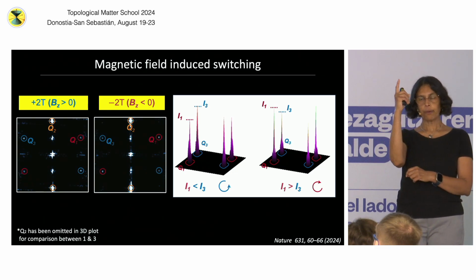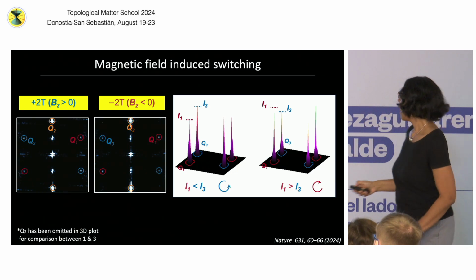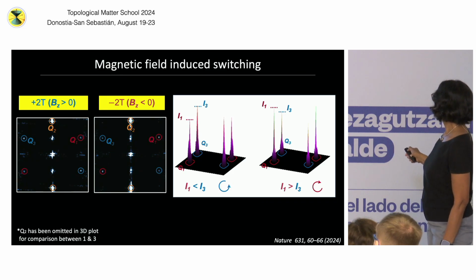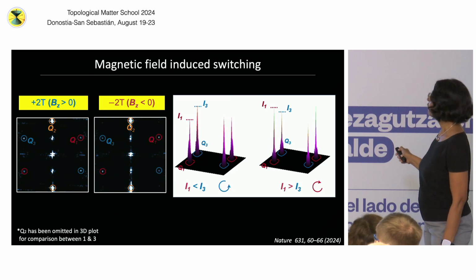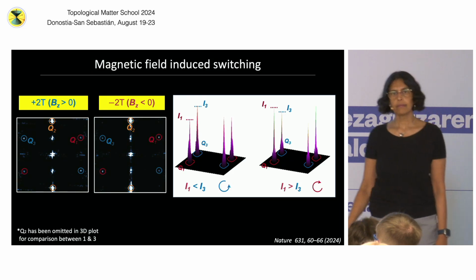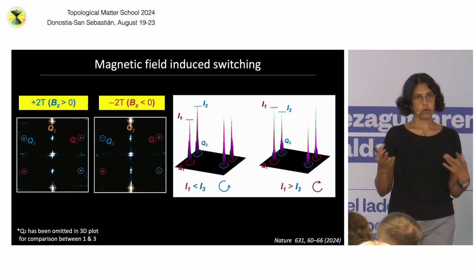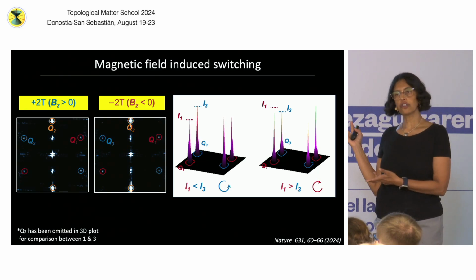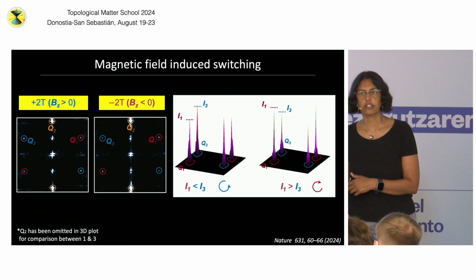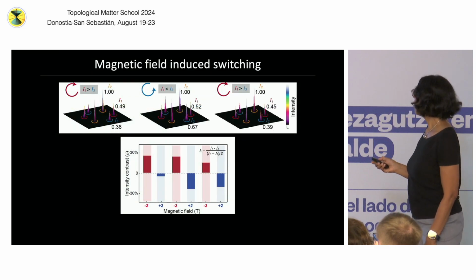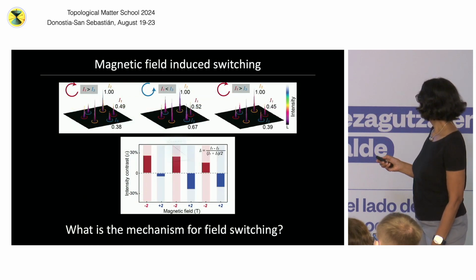So you're applying a field perpendicular to the sample, and you can actually change the relative intensities of the charge density wave peaks, just like he saw. Now the question is, okay, can we show that this is also real by looking at the lattice distortion? And in fact, that's what we see.